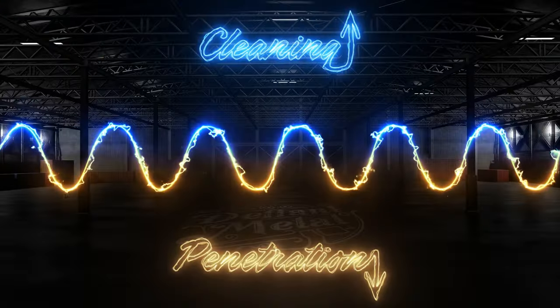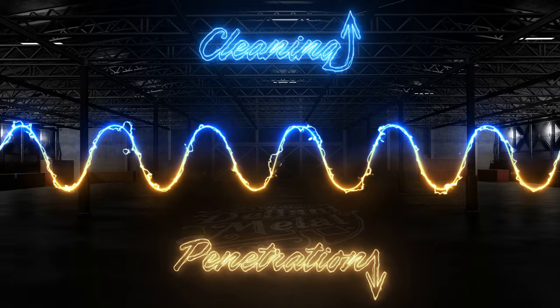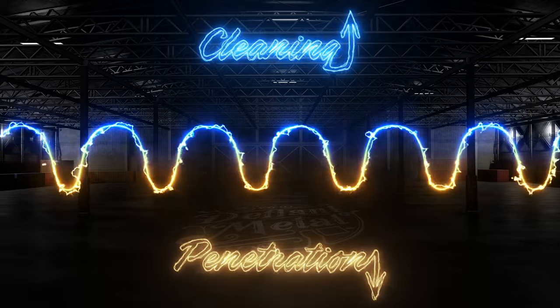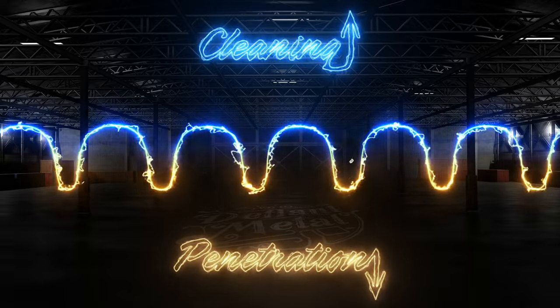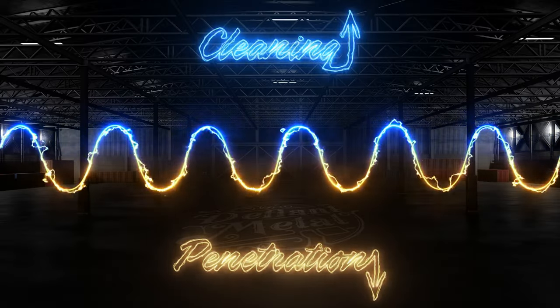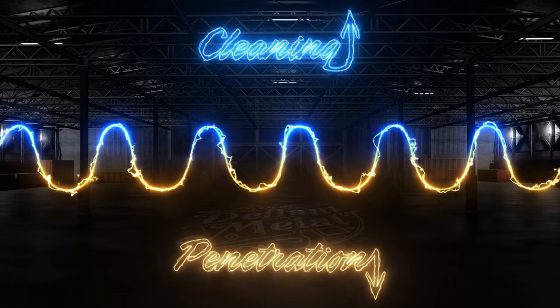No matter how your machine chooses to display it, adjusting the balance affects the amount of time spent on the positive, cleaning side and the negative, penetration side. Right now, our welder is set at a 50-50 equal split between the two, just like it's shown here. If you were to add even more cleaning, like say 80% cleaning and 20% penetration, you would really see the tungsten heat up and start melting away. If we go the other way and set the balance to the original recommendation of 70% penetration and 30% for the cleaning, you can see that it holds the arc much better.